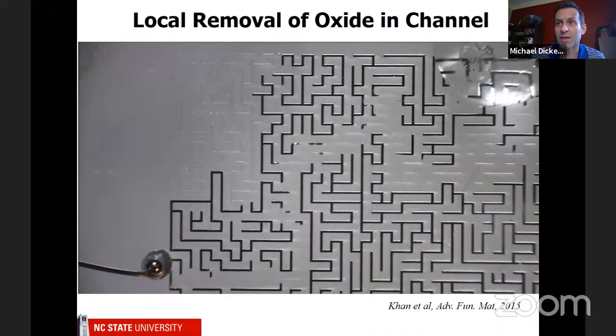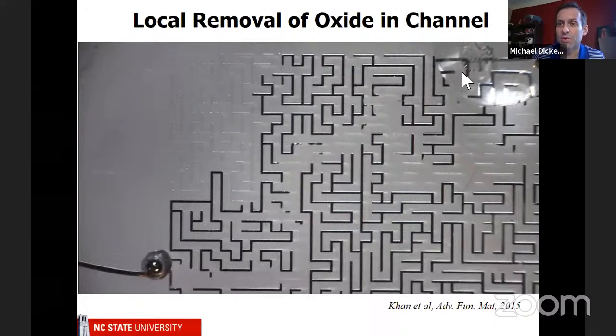So what's happening here is that where this is withdrawing, like right here, the oxide is getting removed by this electrochemical reaction. Now, for this reaction to occur, there has to be water. And so basically, as this thing starts pulling out, it's like a piston, and it pulls this water into this channel. So there is an electrical path from this electrode over to this electrode via water that gets pulled into this path. Okay, so I think that this is cool. It's kind of exciting because you can solve a maze. But the physics are, in my opinion, sort of obvious, because once you remove the oxide layer, the metal simply wants to bead up.